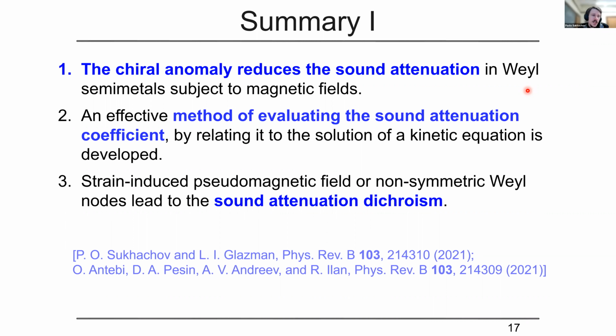Also, on the technical side, we developed an effective method of evaluating the sound attenuation coefficient by relating it to the solution of the kinetic equation. And finally, we found that asymmetry between Weyl nodes induced, for example, by this pseudomagnetic field by static strains might lead to the sound attenuation dichroism. So details can be found in our paper, and actually the papers that appeared exactly at the same time by Antebi, Pesin, Andreev, and Ilan.